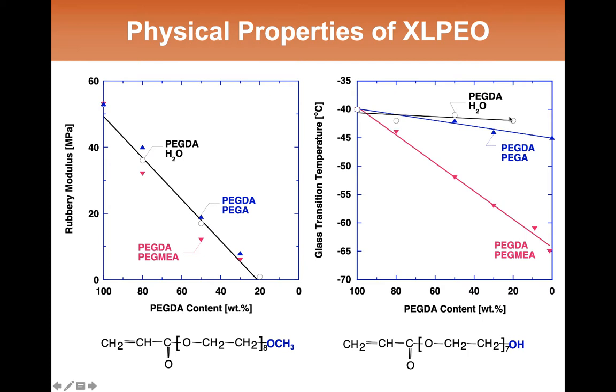In the natural rubber case, as you're introducing those sulfur cross-links, Tg would be changing by more than 100 degrees C as you went from less cross-linked to more cross-linked. Here, the fact that you can dilute out the cross-linker with water when it's polymerized and really drive the modulus, and therefore cross-linking density, to very low levels and have the glass transition temperature not change means that the molecular motions that are giving rise to the glass transition temperature are occurring on a scale that is shorter than any of the relevant length scales for distances between cross-links. Similarly, copolymerizing the cross-linker, the PEG-DA, with the PEG acrylate, which has the hydroxyl groups on the end, shows very little decrease in glass transition temperature as well.